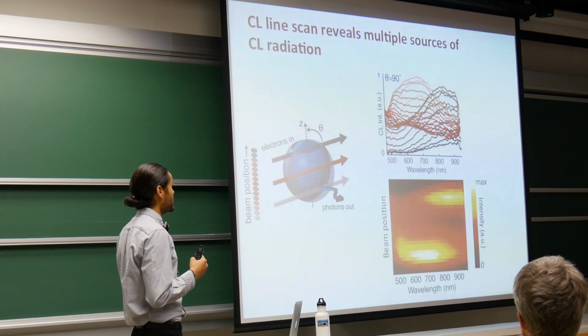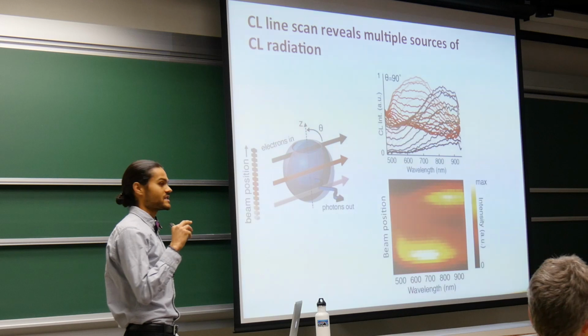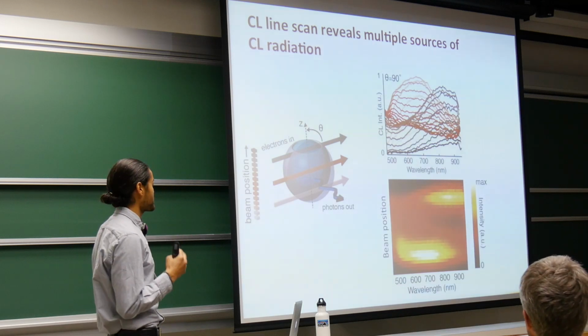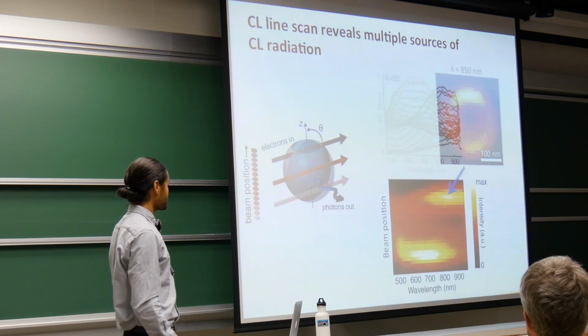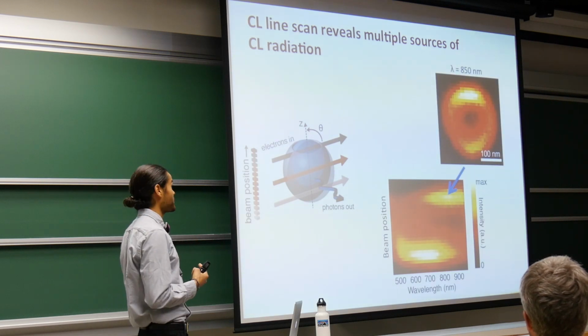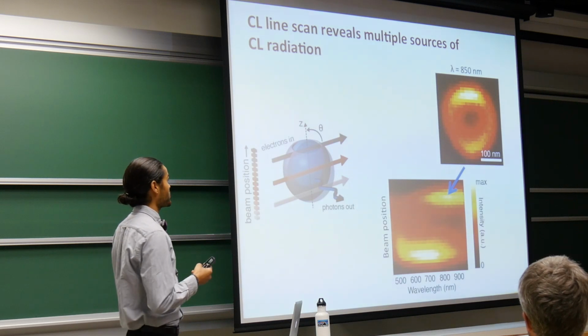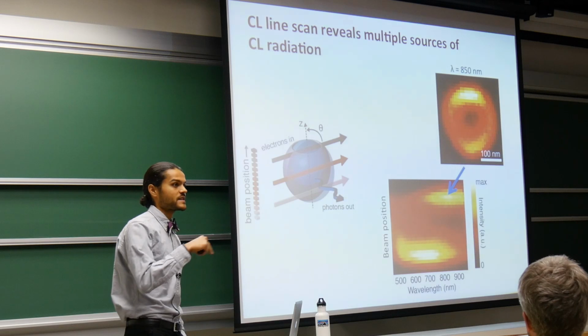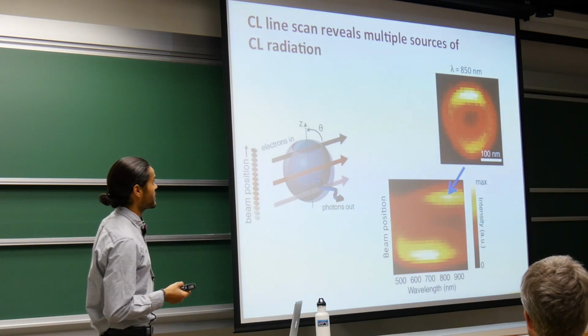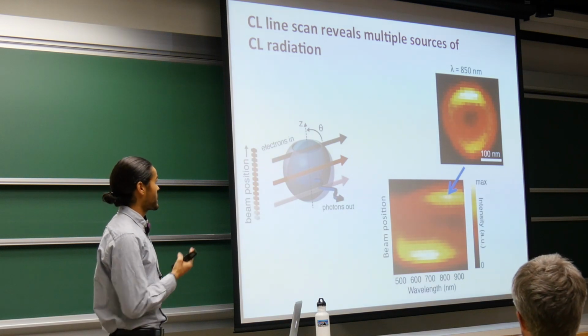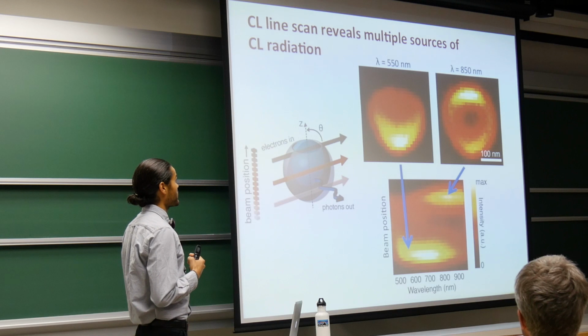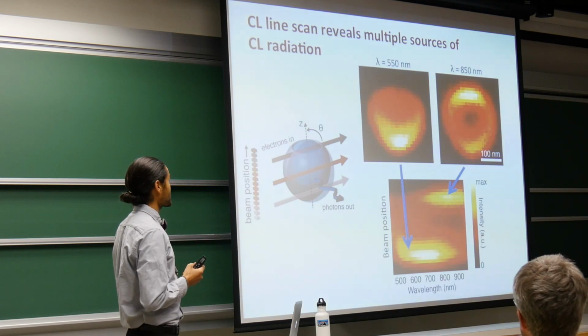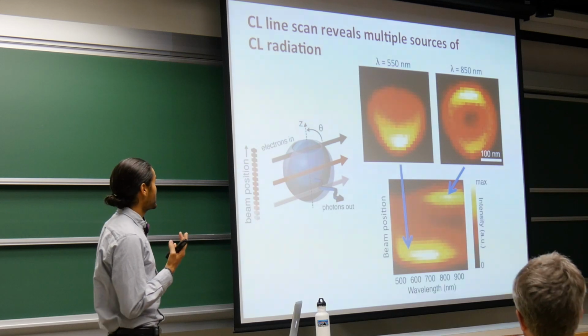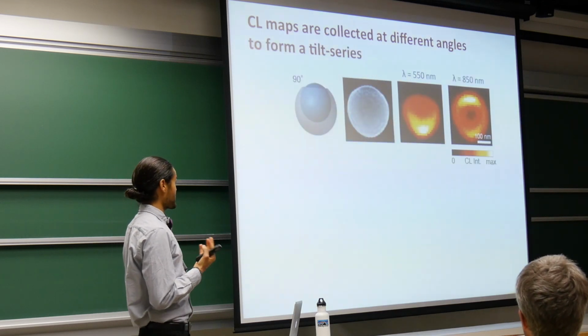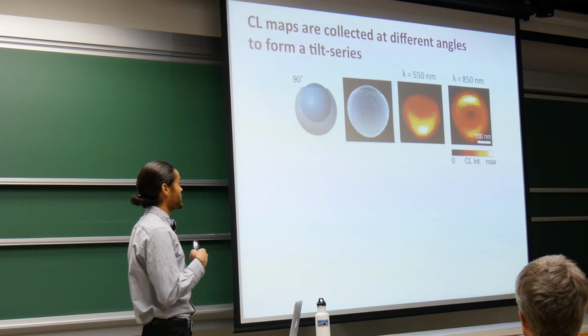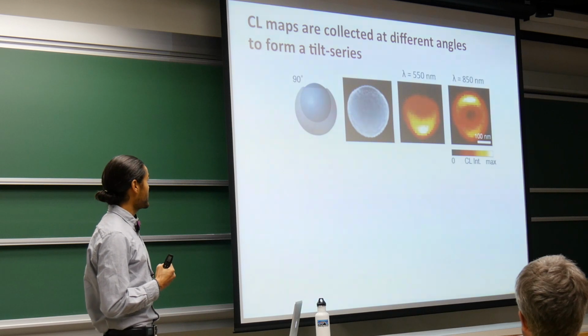Looked at in a slightly different way, we can really see the spatial and spectral segregation of these two different types of luminescent signal in our crescent structure. We can extend this one-dimensional scan into two dimensions. Here we plot a CL scan where we raster the beam back and forth in two dimensions at a wavelength of 850 nanometers, and we can see this strong plasmonic mode supported at the tips of the structure. At a different wavelength, corresponding to the material luminescence, we, as expected, see the signal coming most strongly from the gold shell. As I mentioned, we want to push this into the third dimension. The plots that I've shown you so far are clearly just two-dimensional, but we want to do tomography.